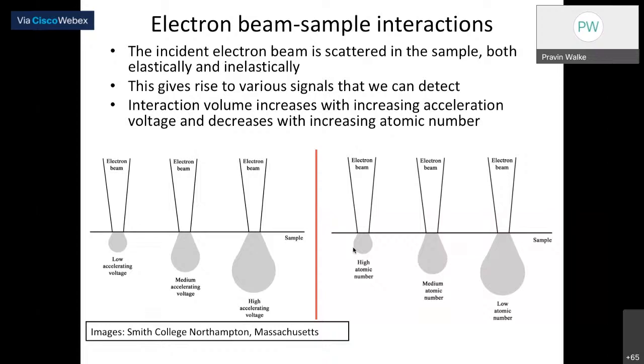So there should be a compromise with the accelerating voltage when you are using SEM scanning of your sample. In that case, you should keep in mind the atomic number of your specimen, number one, and then you have to think about the accelerating voltage. And then also you have to think about how much interaction volume you require, right? So there is a proper synchronization between the interaction volume, atomic number, and acceleration voltage, right? These are the important parameters when we are talking about electron beam and sample interactions.